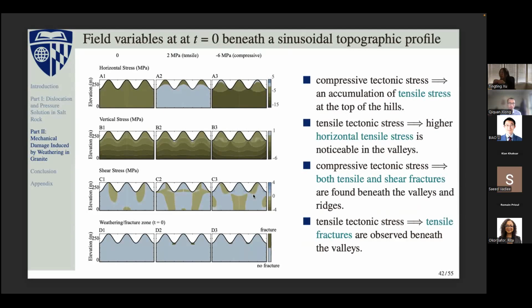And the first simulation result is the field variables at t equals 0. So that means at the moment that we apply all these boundary conditions, we can see the combined effect of the tectonic stress and topographic stress, and how that initiates the fracture. And with that, you can see that for the left column, which is the no tectonic stress case, that means only the lateral earth pressure is applied, and under these simulation conditions, you can see that the lateral earth pressure is not sufficient to open any crack